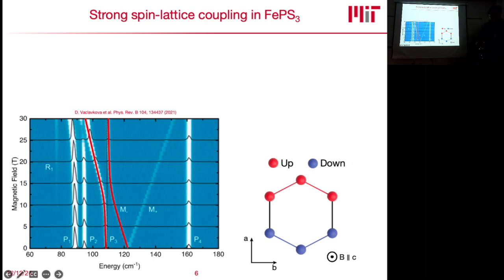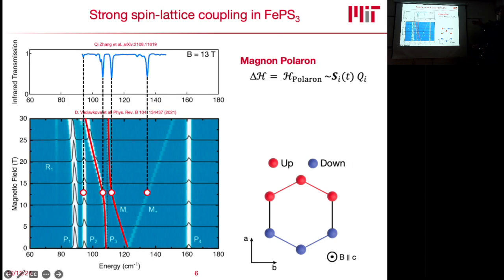What's going on with P2 and P3 at the very high fields? It's basically the same thing. So you also start getting this avoided crossing now with this other mode. Because now, up here, P3 at very high magnetic fields is basically a phonon again, it's not hybridized. But then your magnon starts coupling to P2. And so now this starts hybridizing into this collective, hybrid mode, what people like to call a magnon-phonon in this case. And what I'm showing here is Raman scattering.